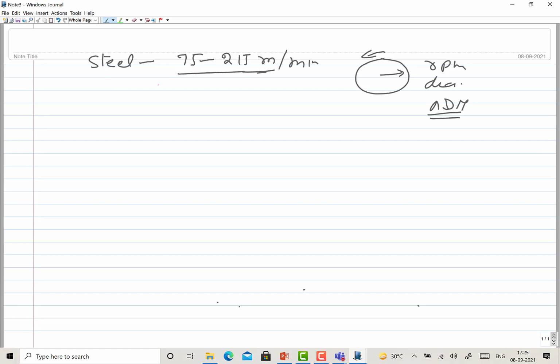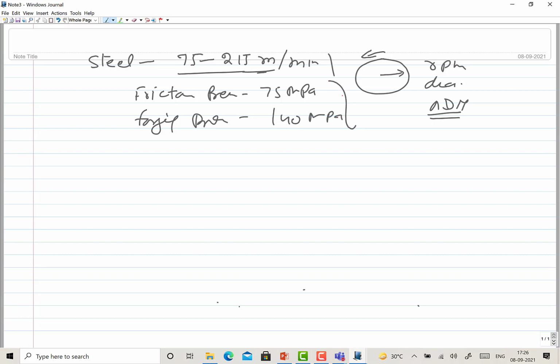Okay, and the forging pressure that is applied, like say the typical friction pressure is of 75 MPa, and the forging pressure which is applied is of 140 MPa. So these are the kind of typical parameters for the steel welding. So if your job size is small, what should be the RPM that you need as compared to the job when it is of the large size?